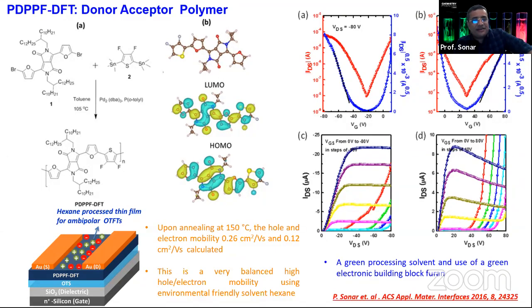The industrial community usually, if you want to make this a commercial entity or do the licensing, and actually some of my DPP we licensed to the US based company called Corning, from the Singapore work, they were asking, can you change, instead of chloroform, to an environment friendly solvent? Then we came up with a non-chlorinated solvent called hexane, and we made this new material, and even using hexane, in this case we can achieve a very good hole and electron mobility again with an ambipolar type of polymer.